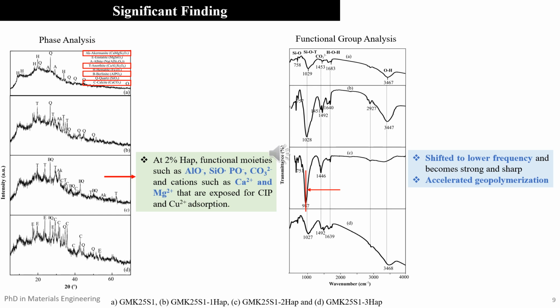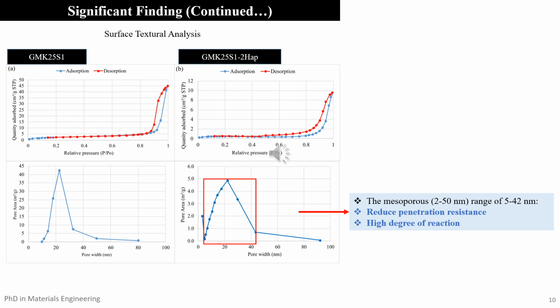Besides, based on the functional group analysis, the main adsorption band of geopolymer at 1029 was shifted to 987, indicating the accelerated geopolymerization, providing more functional groups and cations for the adsorption process. In addition, with the incorporation of 2% of hydroxyapatite, the pore size distribution of geopolymer exhibits a broader size in the range between 5 to 42 nanometer, highlighting a more mesoporous structure has been formed. The mesoporous structure is beneficial for the adsorption process as it reduces the penetration resistance during adsorption. Besides, the mesoporous structure also highlights a high degree of reaction of geopolymerization, consistent with the FTIR analysis.